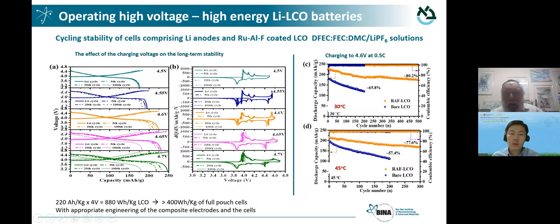Now, there is of course the question of voltage. Here I show options for polarization from above the conventional one, going up to even 4.7. We came to the conclusion that for LCO, 4.6 is optimal because with 4.6, we can extract very high specific capacity, starting with 220 at least, and it can be well stabilized. And here I can show you stabilization by a coating which includes ruthenium. It appears that ruthenium provides a very good result, but now we have other methods which are much cheaper and also do a very good job.